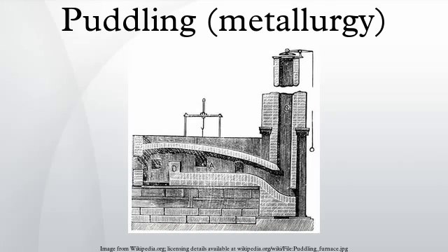This problem was resolved by combining puddling with one element of a slightly earlier process, involving another kind of hearth known as a refinery or running-out fire. The pig iron was melted in this and run out into a trough. The slag separated and floated on the molten iron, and was removed by lowering a dam at the end of the trough. The effect of this process was to desiliconize the metal, leaving a white brittle metal known as finer's metal. This was the ideal material to charge to the puddling furnace. This version of the process was known as dry-puddling and continued in use in some places as late as 1890.